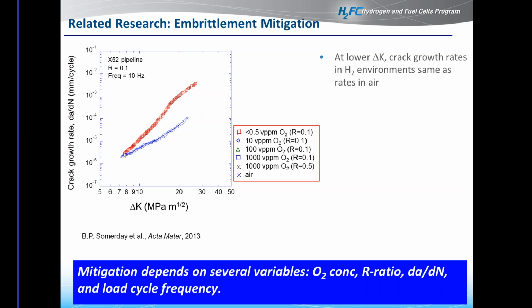And what we did was we took fixed amounts of oxygen mixed in. So in other words, 10 ppm, 100 ppm, and 1,000 ppm oxygen. Those oxygen species were essentially introduced to the hydrogen gas, and we performed the tests in those environments. So first, looking at 10 ppm oxygen, we didn't see a significant change between that and the high purity hydrogen. So this told us that we didn't really have a lot of oxygen already pre-adsorbed onto the surface.